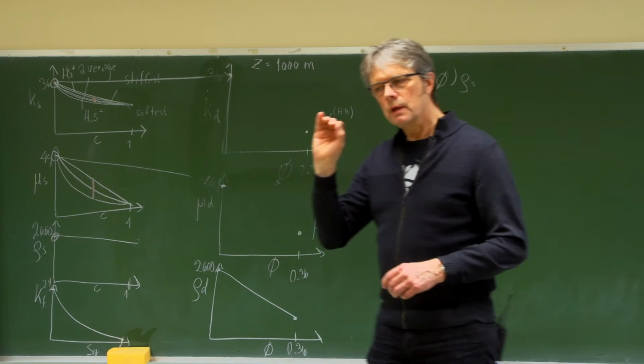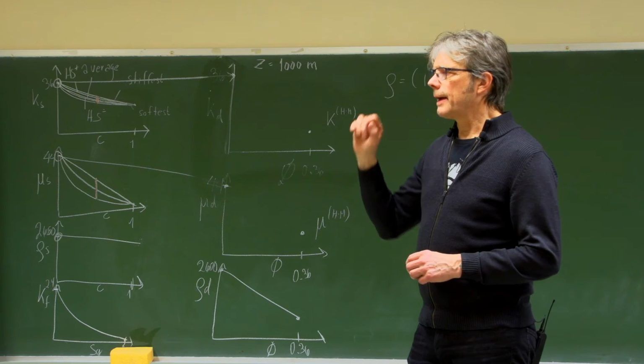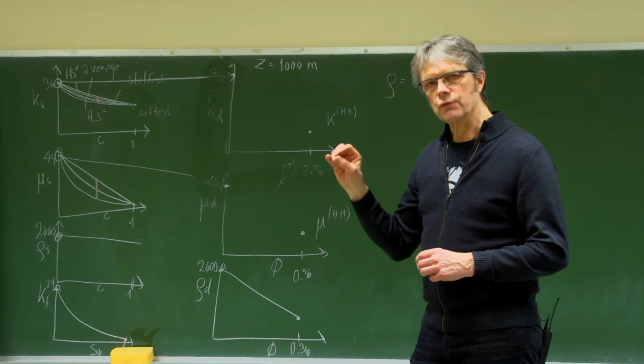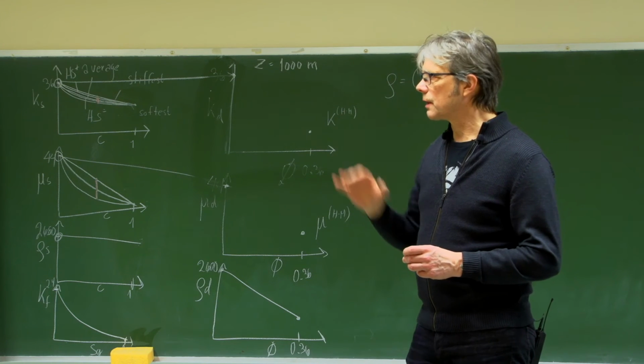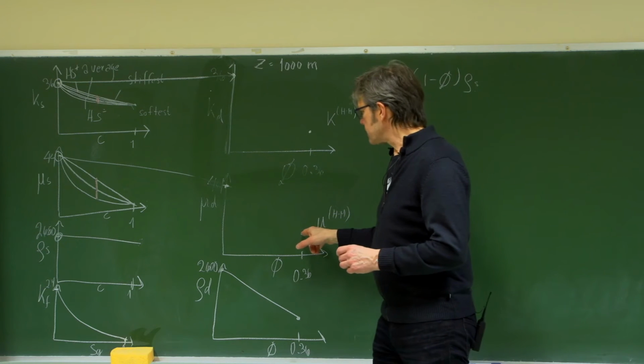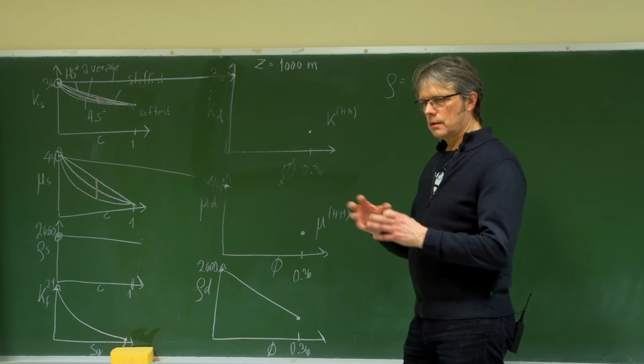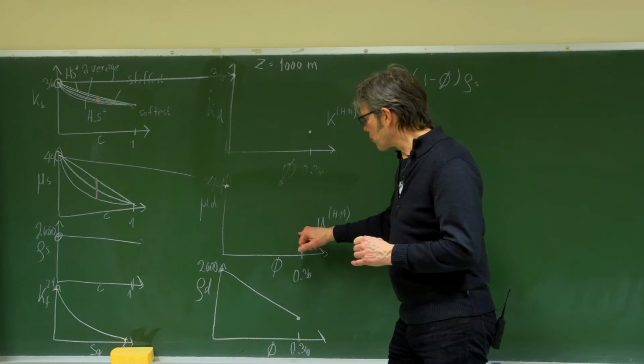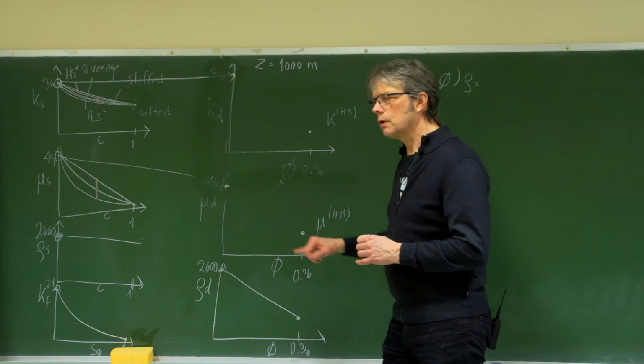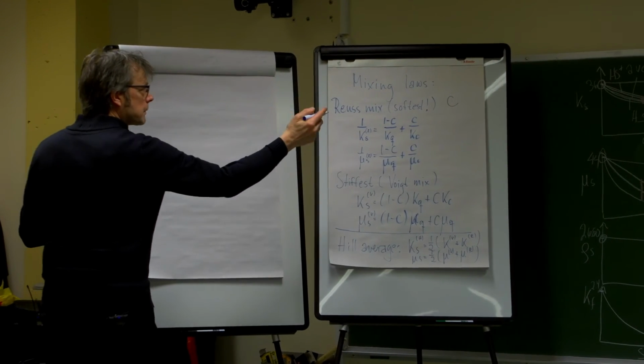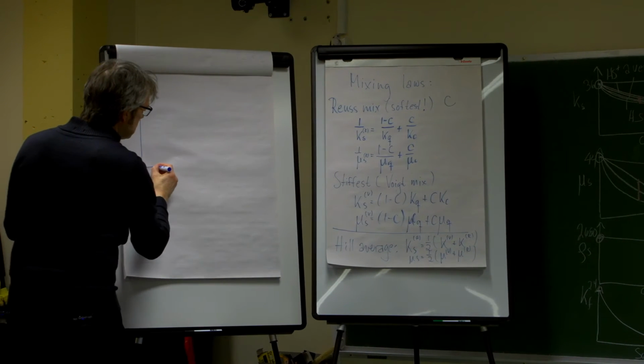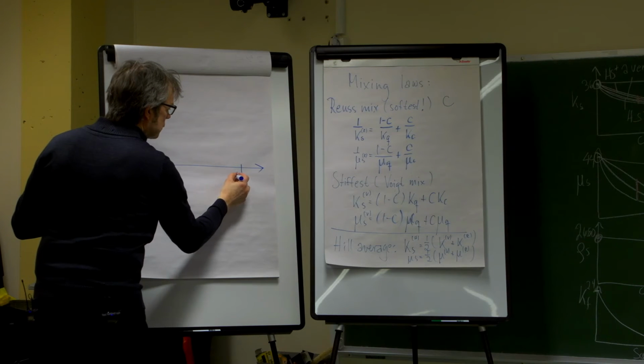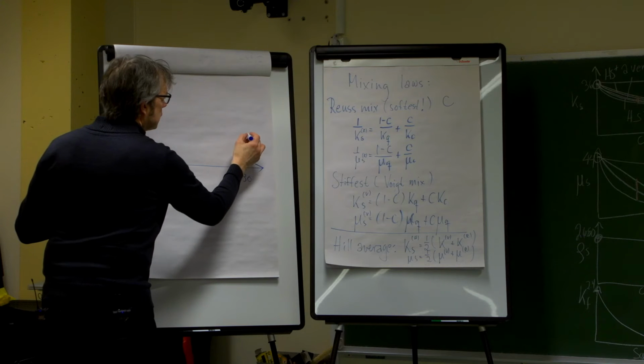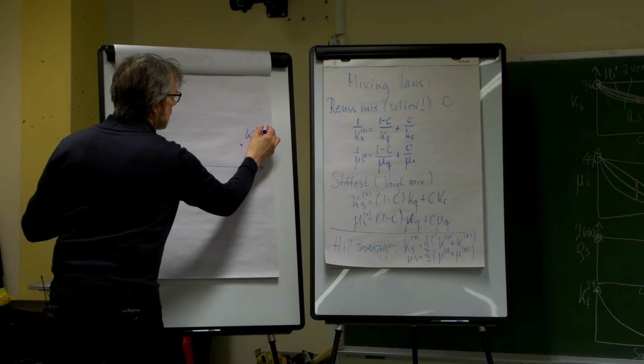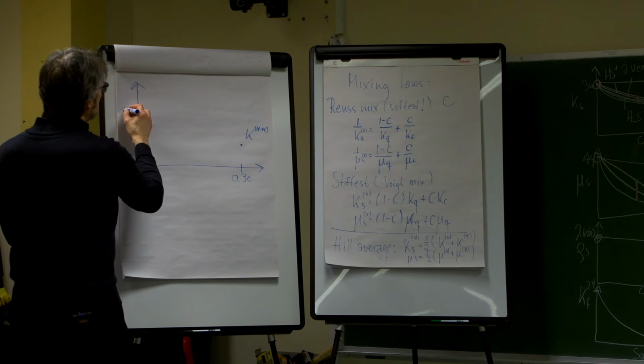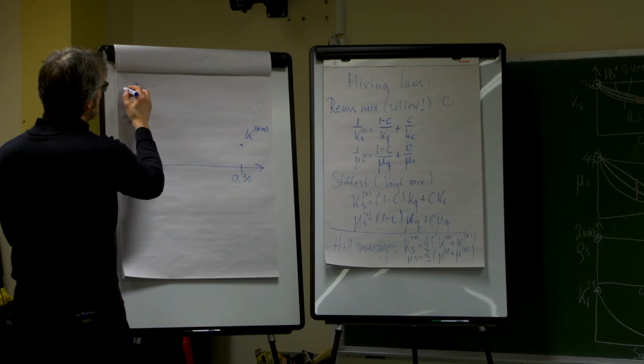And now we can add some geological interpretation to our choice. Remember this soft sand model? We have already discussed that, and that just means that, okay, if I use a Hashin-Shtrikman lower bound, I'm in fact trying to reduce the porosity by poorer sorting. So I'm just copying this bulk modulus over here. We had a porosity of 36 here. I had my Hertz-Mindlin point here, and then this is the K dry. And then I have my mineral point at 36 here, okay?